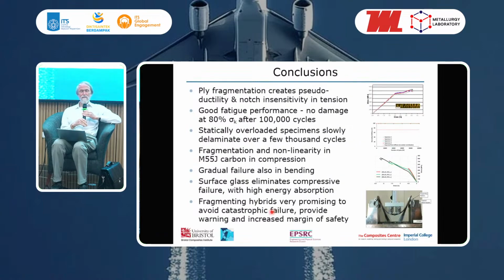So in conclusion, ply fragmentation can create ductility and notch insensitivity in tension. We see good fatigue performance with no damage at 80% of the knee point strain even after 100,000 cycles. And even specimens which had been statically overloaded only delaminate quite slowly over a few thousand cycles. We also see fragmentation and non-linearity in the M55J carbon in compression, and we see a gradual failure also in bending. The surface glass can eliminate the compressive failure and give us very high energy absorption. So overall, I would say that these fragmenting hybrids are very promising as a way of avoiding catastrophic failure and providing warning and increased margin of safety.